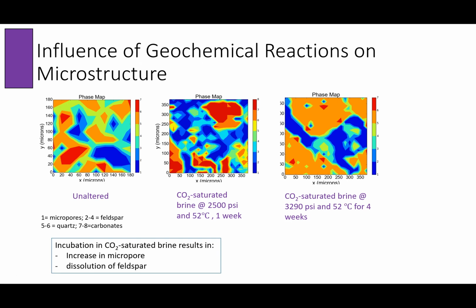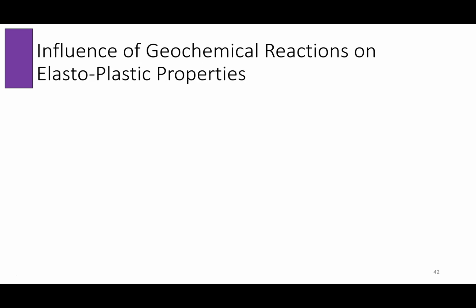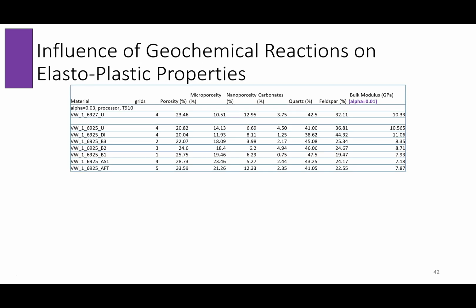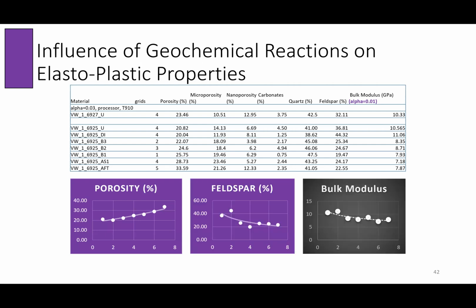But the good thing is that using this multi-scale approach that incorporates micromechanical modeling and depth-based nanoscale mechanical testing, we are able to have this connection between geochemical reaction and microstructural and compositional changes. So then we can try to think, what is the influence of geochemical reaction on the elastoplastic properties in this case? We can quantify the fraction of each phase, carbonates, quartz, feldspar, and then the different porosity in terms of microporosity and nanoporosity, and we can tie it to a value of the bulk modulus. So we can just show what is happening.